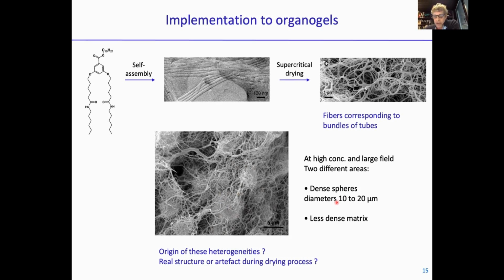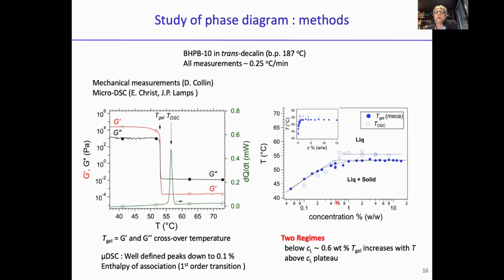And to explain that, we decided to come back to some thermodynamic studies. What we did is we mapped out the phase diagram, like here, by two methods. By differential scanning calorimetry, you can see, we heat the gels and we see when the gel melts. And here by rheology, we measure both the elastic and loss modulus while we heat, and when G prime becomes lower than G double prime, the crossover point shows that we have a transition from a solid-like material to a liquid.